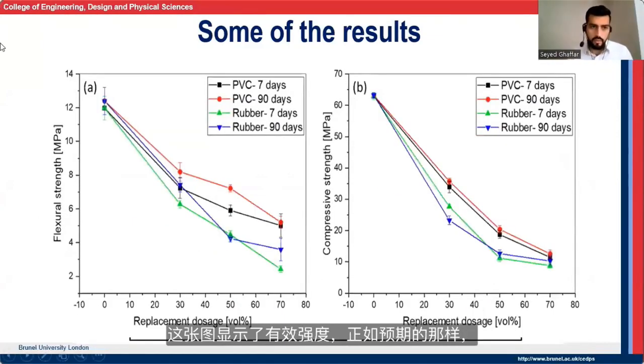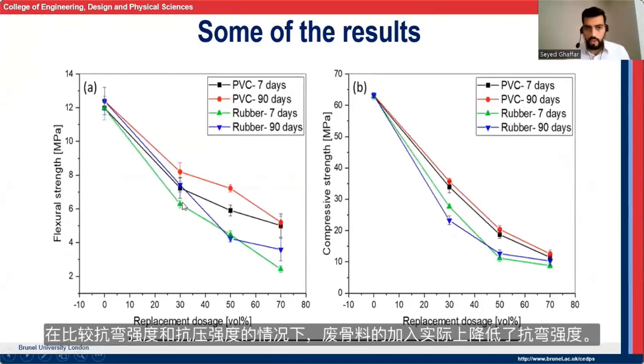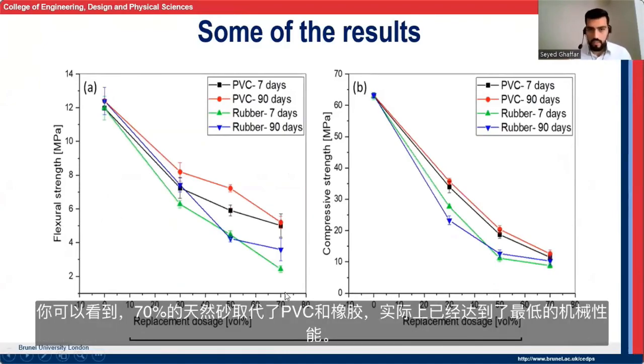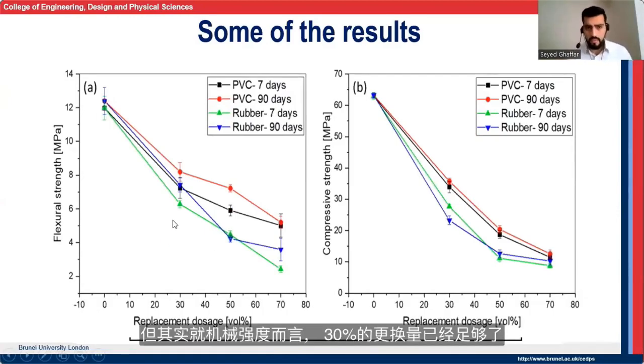So this graph here shows the flexural strength. Of course, as expected, the addition of waste aggregate actually dropped the strength, in the case of flexural strength and compressive strength. And you can see that the 70% replacement of the natural sand with PVC or rubber has actually achieved the lowest mechanical properties. But the point here is that 30% replacement is adequate in terms of mechanical strength.